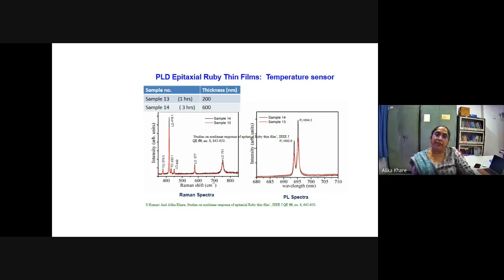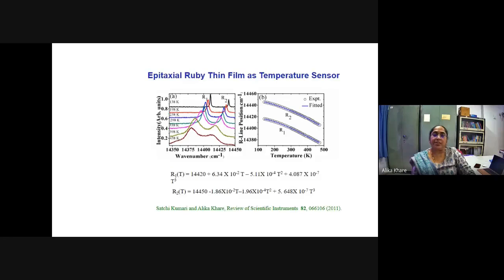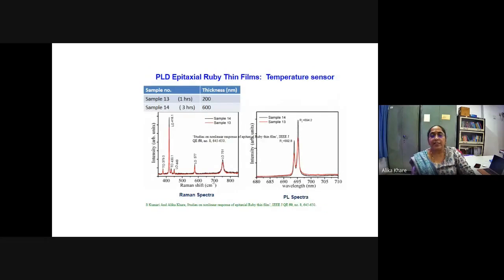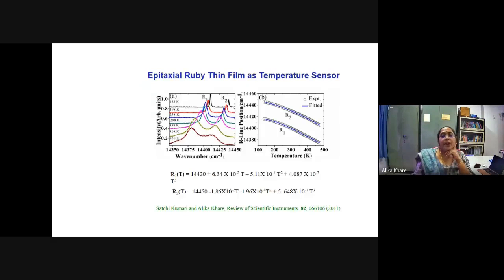Now we have demonstrated this as a photonic temperature sensor. These lines are dependent on temperature - both the location and the separation depend on temperature, though it is not a very linear dependence. Here is the variation of the R1 and R2 lines as a function of temperature.